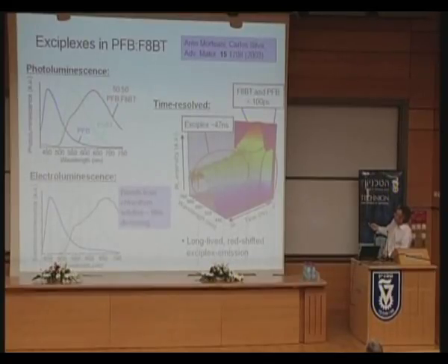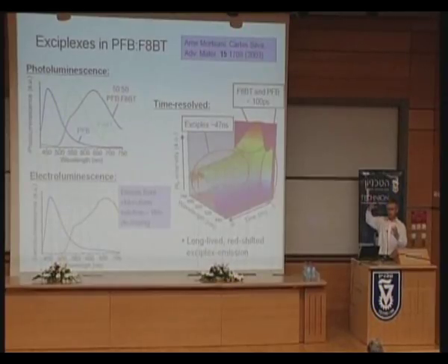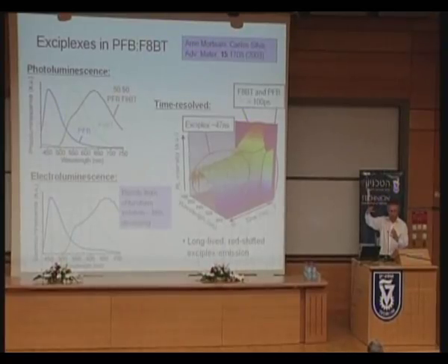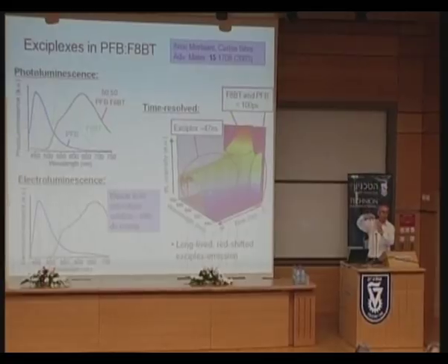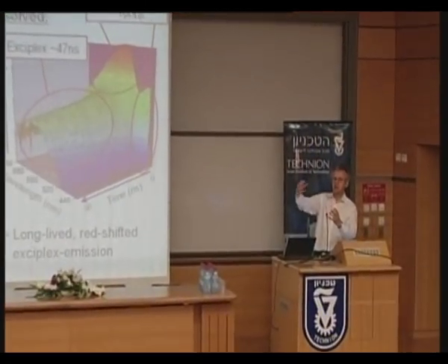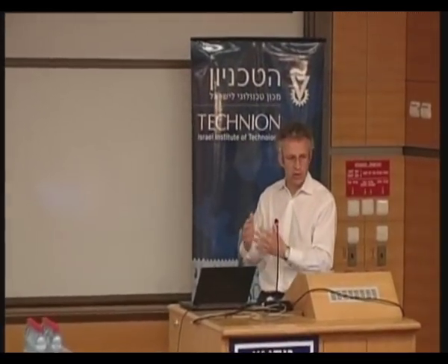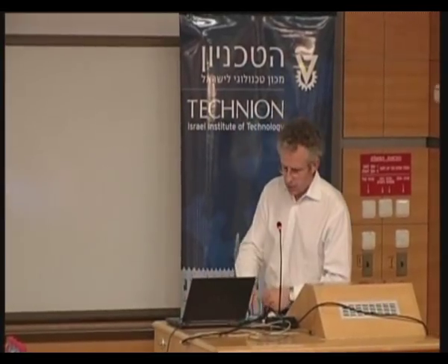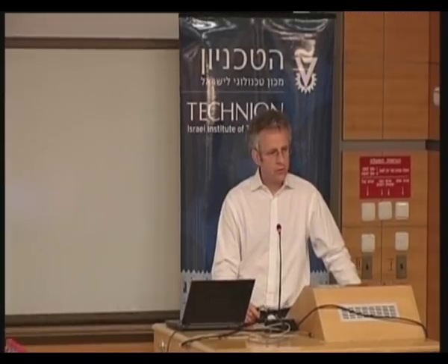Now, in the time domain, what we see is a 100-fold slowing down of the emission. Typically, if you have an excitation just on one molecule, it has a radiative lifetime of a nanosecond, 10 to the minus 9 of a second. What we measure here is a radiative lifetime for this red emission. In this example, the actually measured time is 47 nanoseconds. One can work back that the radiative lifetime is about 100 nanoseconds. It's been slowed down. So we've got redshifting and slowing down, a very good characterization of the electron and hole across the heterojunction but not able to escape one another. And accidentally, for these particular material systems, there's just enough overlap of wave function of electron and hole across the heterojunction that we can still see this radiative transition. So it's a really good signature of what actually is generically the issue in getting good charge separation. So how does this then play back on the problem of making a solar cell?